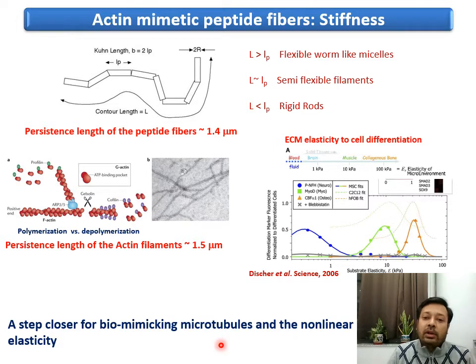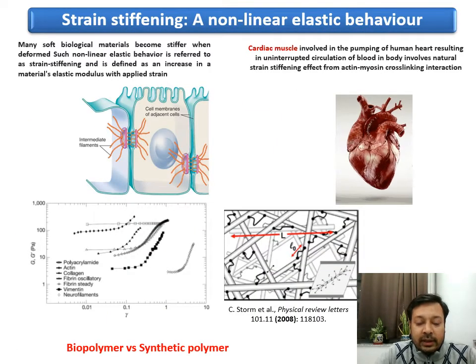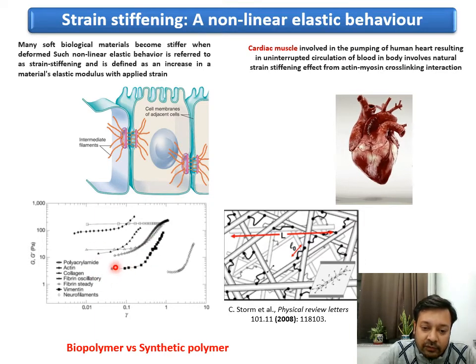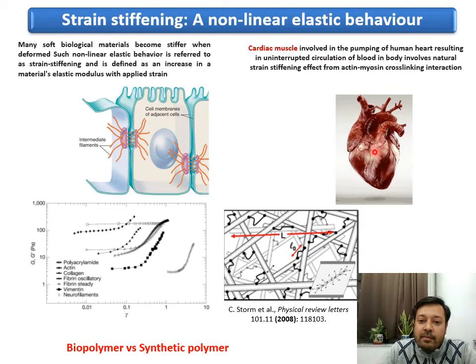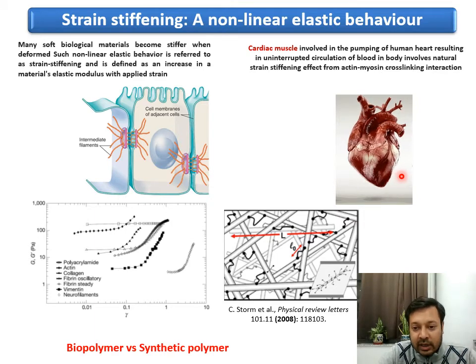And this is very important, particularly if you make a material or extracellular matrix from synthetic peptides, so you can actually tune the ECM, the extracellular matrix elasticity, and that has a role in stem cell differentiation. So we thought that's a very interesting idea, because if you look at many of these biopolymers, they show this kind of stiffening response upon applied strain. And this is very important, particularly in the case of cardiac muscles, which can pump the blood in an uninterrupted fashion, and that stems from the ATP mediated actin myosin cross-linking, resulting in a contractile material.